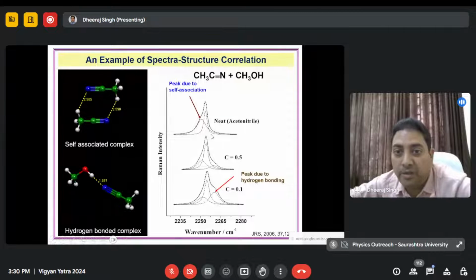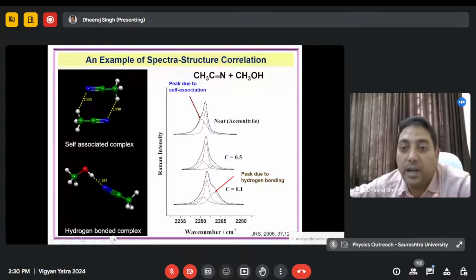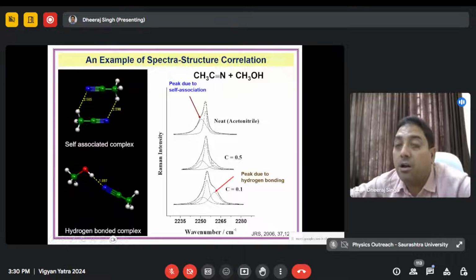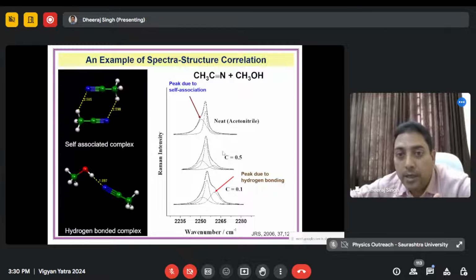Suppose now we are going to mix 0.5 mole fraction, or 50 mole percent, methanol or ethanol alcoholic solvent in this acetonitrile. Let us see how the spectral structures are correlated. Now, if 50% methanol is mixed in this acetonitrile, then what happens? The peak intensity of the dimer will break. That's why the intensity of this dimer is decreased.